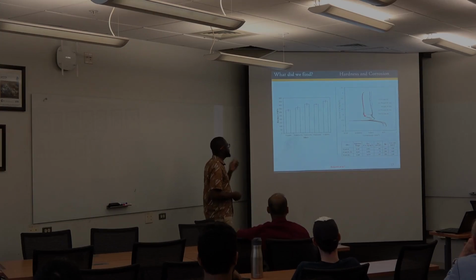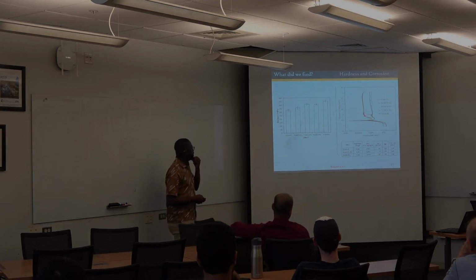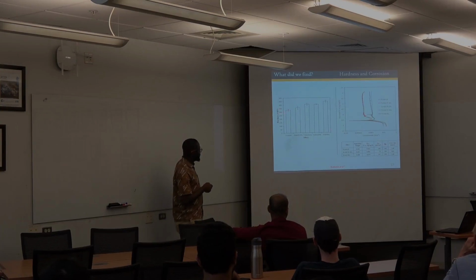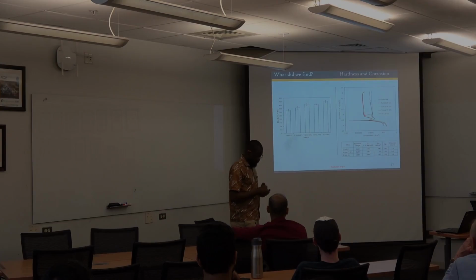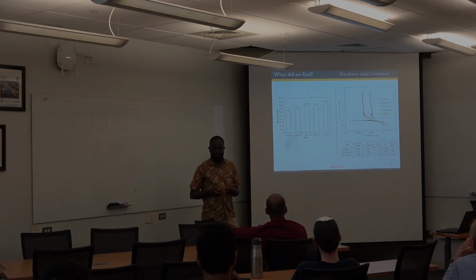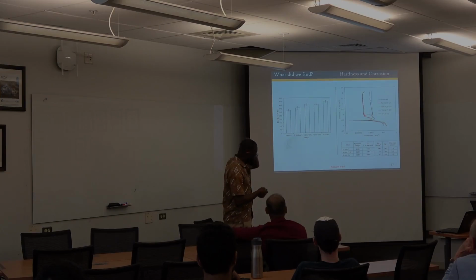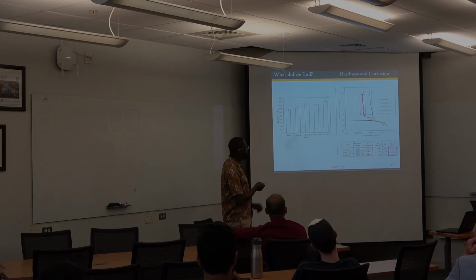And again, we looked at the hardness of this alloy, and we see that it compares really well with that of commercial grade titanium, and this is just in the cast mode. We haven't done any more processing at this point. What is really interesting, and I hope that Prof. Rajiv can give some feedback or we can work on this, is that in terms of corrosion, if you look at all these iron-containing alloys, the passive region is actually more on the left compared to the alloy that contains either just iron or just vanadium.